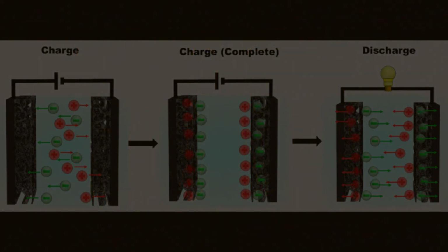An important aspect to take into account is the device's biocompatibility. It should be noted that this concern is important, especially when carbon-based surfaces will come in contact with complex fluids and tissues. The MWCNT sheets could be coated with biocompatible materials, such as PEDOT:PSS polymer and ferritin. This was seen in an in vivo application where the abdominal muscle of a mouse was stitched with a suture resembling a micro-diameter-sized fiber supercapacitor.